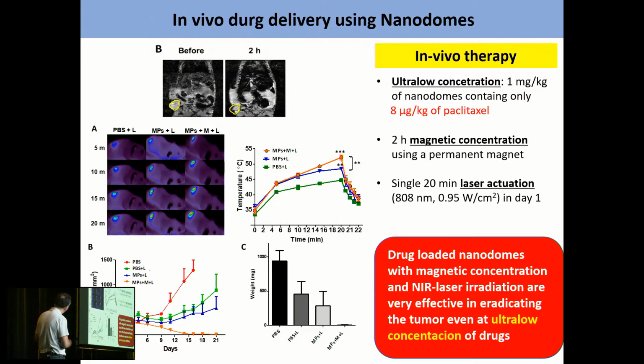And then what we did is to put a magnet close to the tumor for 2 hours to concentrate, and you can see that up here. In yellow, that's the tumor, and you see before it's all gray, and after 2 hours it becomes black in here, meaning that we concentrated all the particles in the tumor. Then we use the laser